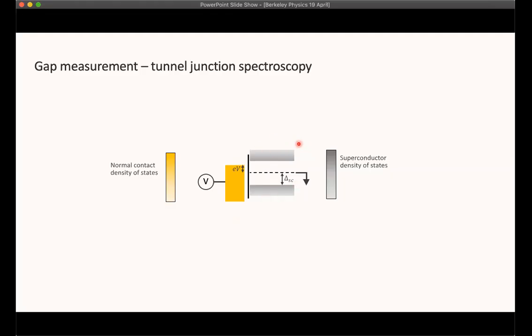And on the other side of the barrier, if we have a superconductor, well, we've got something more interesting going on. We have something like a BCS density of states where there should be a gap for which no conductance happens. And then above that gap, we expect a peak in the density of states at the gap edge. And so if we apply a voltage across this junction, then we can actually tune the relative Fermi levels on one side or another and probe the different points in energy of the density of states of the superconductor.